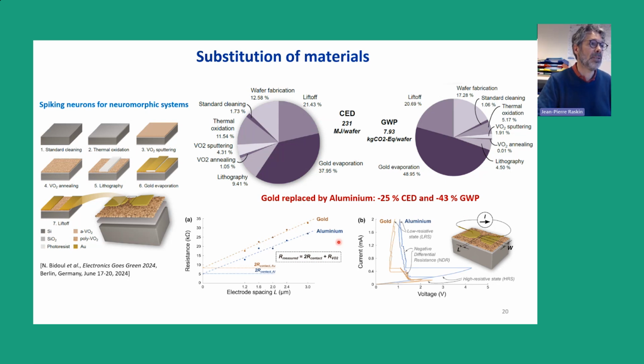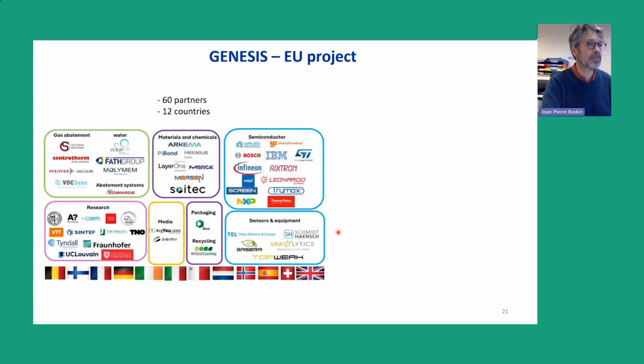Sorry. Of course, what we have to do is be sure about the performance and the reliability of this kind of spiking neurons. And this is what we have tested, and we have demonstrated that we can obtain the same performance, the same reliability, changing the contact from gold to aluminum for this kind of device. Then substitution is, of course, a pathway to reduce the impact of the microelectronics industry.